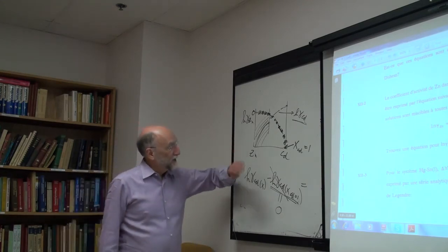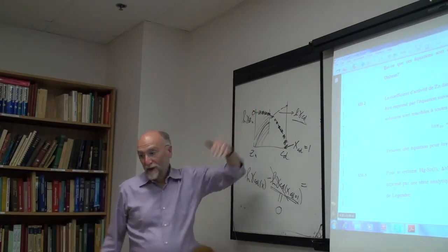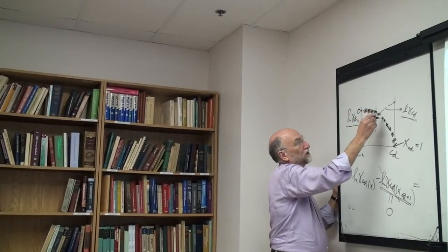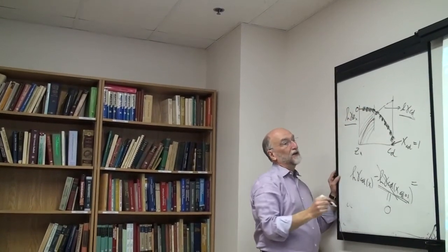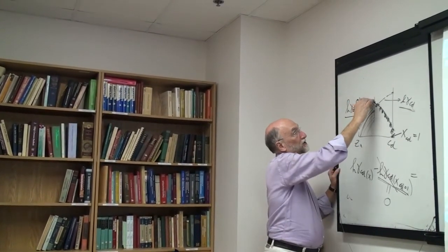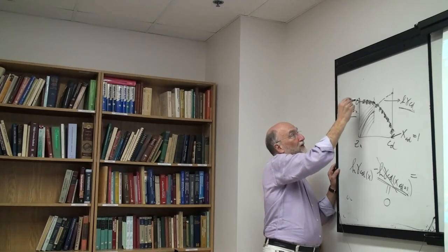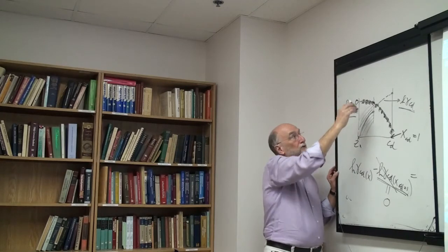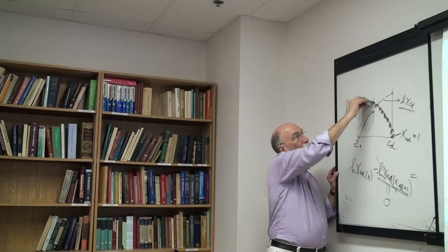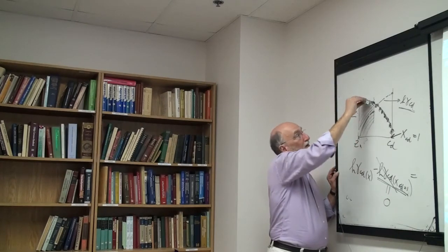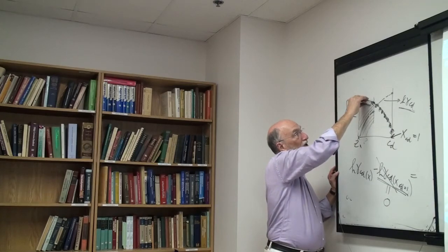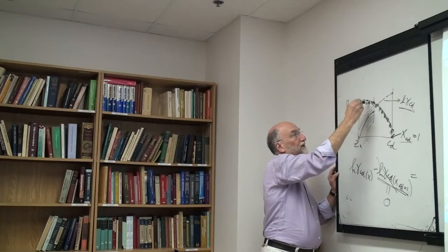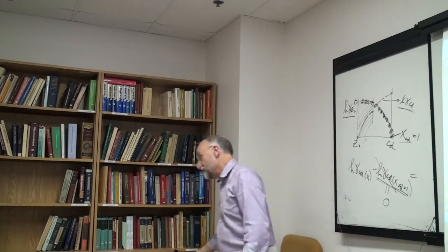And this can actually be one last thing before we have the break. It depends on the slope. Say you measured log gamma zinc. We're doing this now, the endpoint's fine. We measured this thing over the entire composition region. We're integrating back here to get log gamma cadmium. It depends on the slope of this curve of log gamma zinc. Now, as you approach pure zinc, the slope is almost zero because you're in the Raoultian region. So the slope only varies very slightly over a composition region here. But if you look at the Gibbs-Duhem equation, that very slight change in slope has a really big effect on log gamma cadmium, because in this region up here, log gamma zinc varies very slightly with composition.